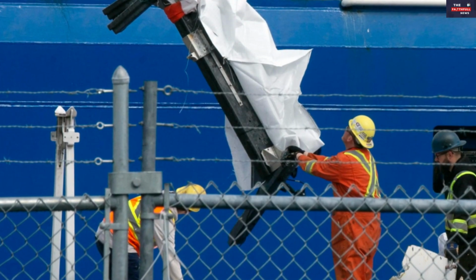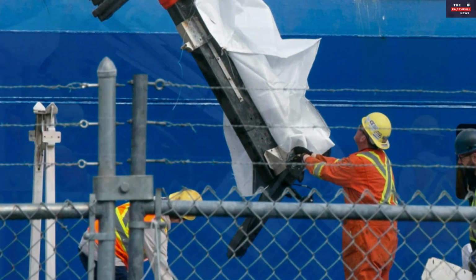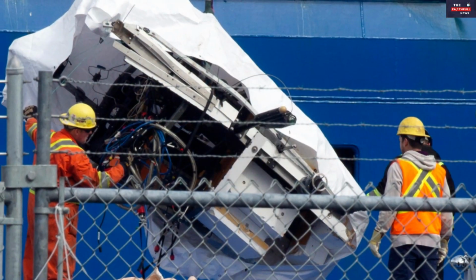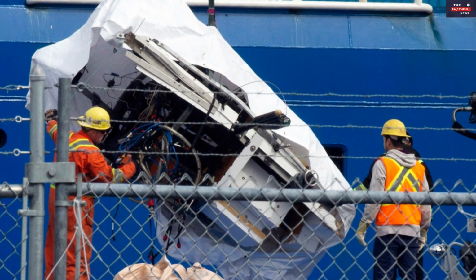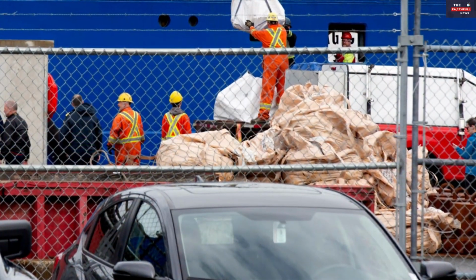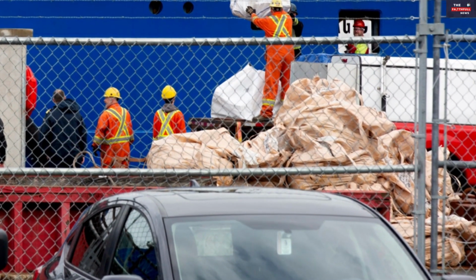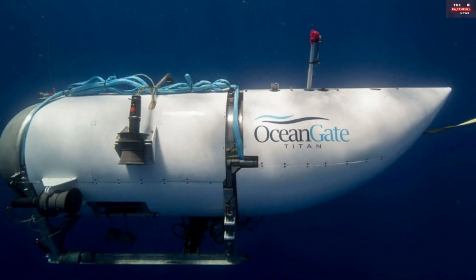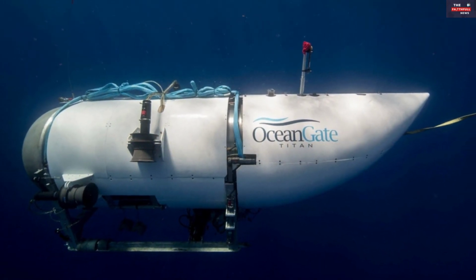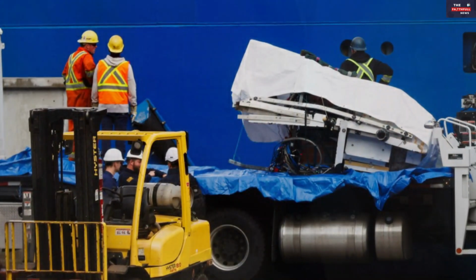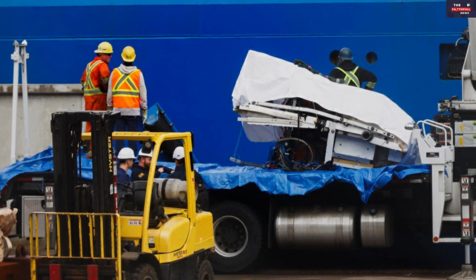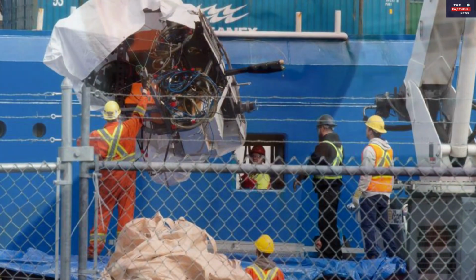Dr. Graham Jones explained following the salvage of the wreck, investigators will begin to look for a cause of disaster in locations where cracks are usually found. Typically, he said, this could be at joints of the vessel and where the greatest flexing is occurring. But certain patterns of cracks on the vessel and their locations can signify what exactly went wrong, and when. Dr. Graham Jones said, the crack could be brittle, or ductile, and related to fatigue and delamination. By scanning under an electron microscope, you can see the fatigue and confirm the speed and direction of the cracks.